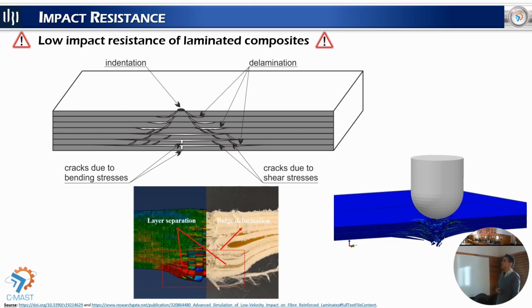In the surface that is impacted by the object, we can see, or sometimes it's not so visible, a small indentation in the structure, in the place where the object impacts it. But there is a propagation of the damage through all the structure that is not visible in the upper side of the sample that is hit. And in the opposite side of the surface that was hit by the object, typically catastrophic damage occurs. Fiber breakage, delamination, and this type of damage will really compromise the structure in its function.